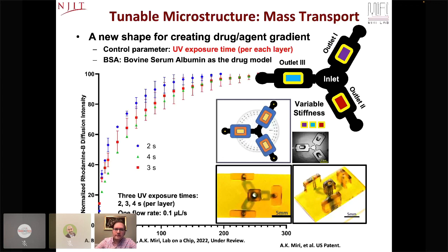So by changing the exposure time during the fabrication from 2 seconds to 4 seconds for a specific intensity, for a specific hydrogel concentration, you can see the particle diffuse or transport at a different rate when it goes from one to another. And we can make this as a device with different chambers in the same system with a single inlet, but different outputs, and each output is linked to that specific, for example, in this case, the diffusion rate or mass transport rate that you can control.